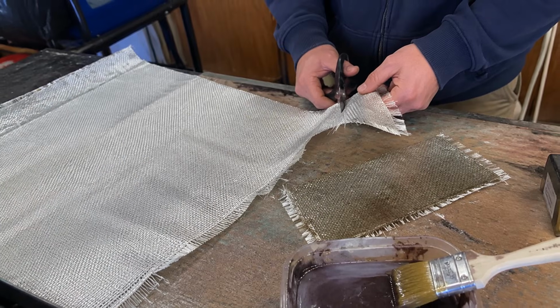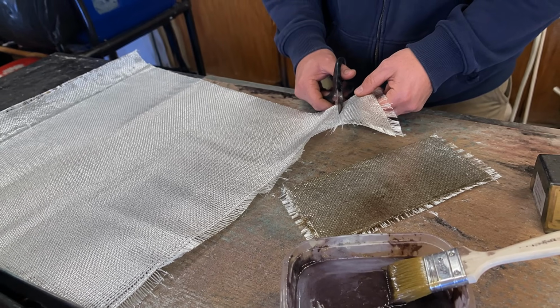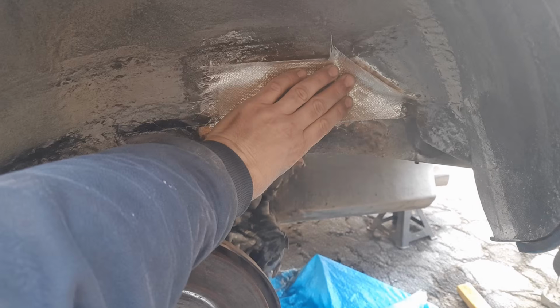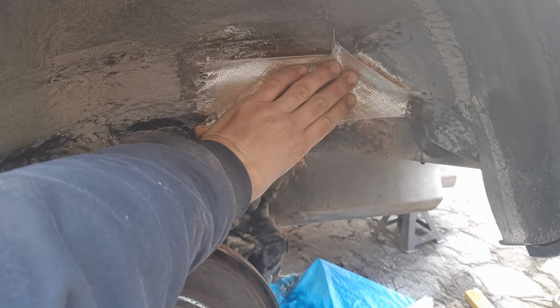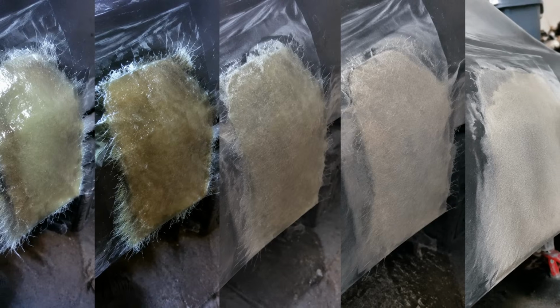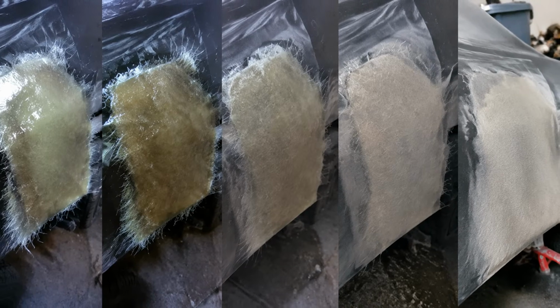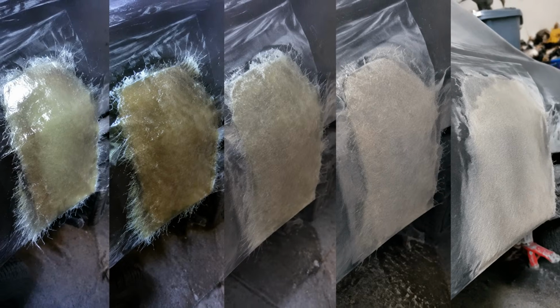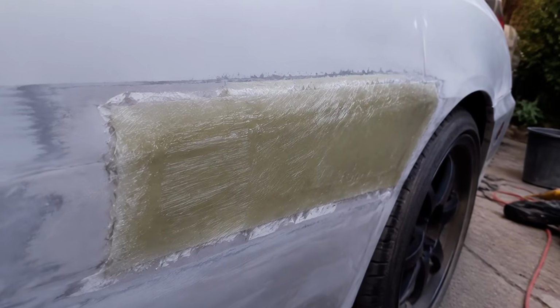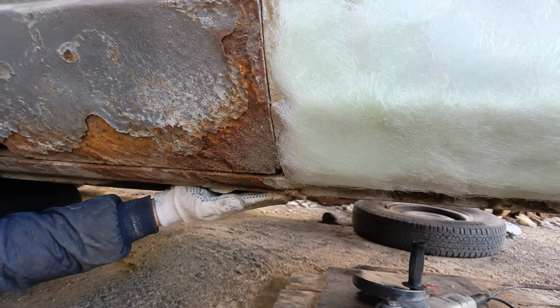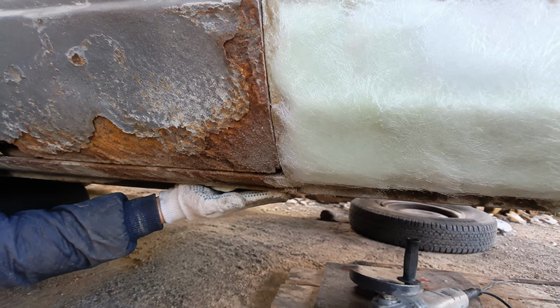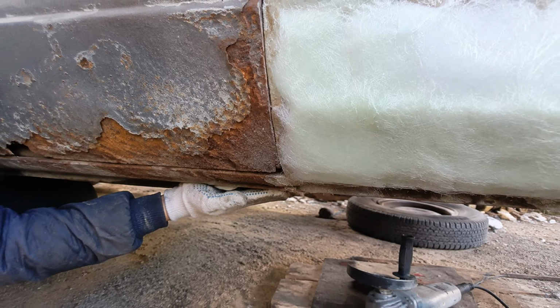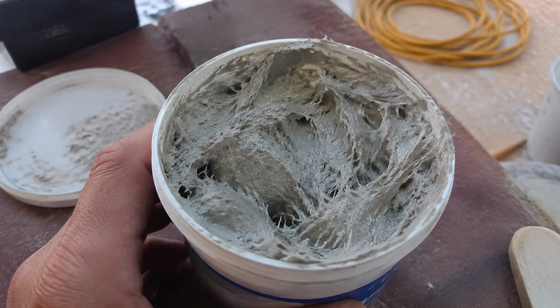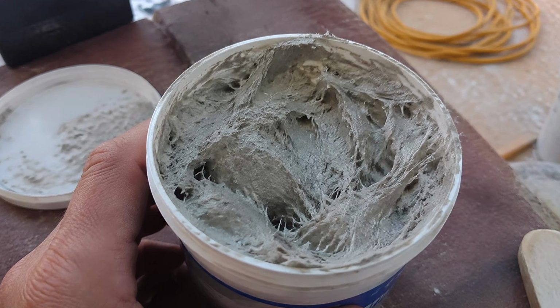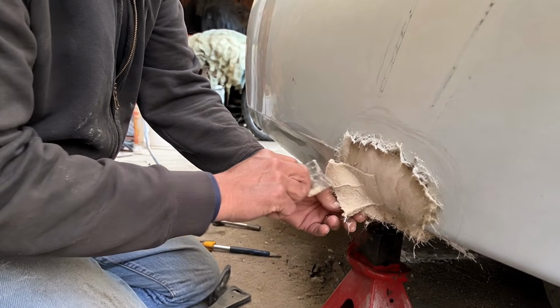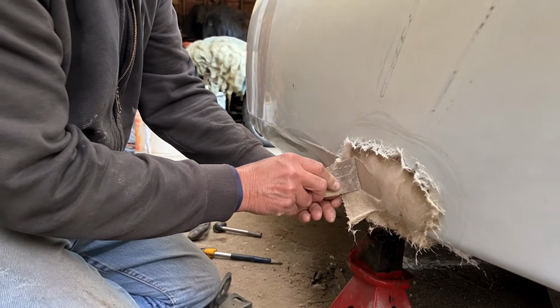You cut the cloth a little bigger than the hole, wet it out with the resin, and lay it over the opening, often from behind if you can reach, so the patch gets drawn in flush. The glass and resin cure into a hard, rigid bridge. And here's the quiet advantage nobody mentions. Fiberglass doesn't rust. Ever. You've replaced a patch of steel that wanted to corrode with a patch of glass and plastic that physically can't. Long strand fiberglass filler is nearly as strong as the sheet metal around it. For a wheel arch or a lower fender done properly, that's a repair that'll hold for years.